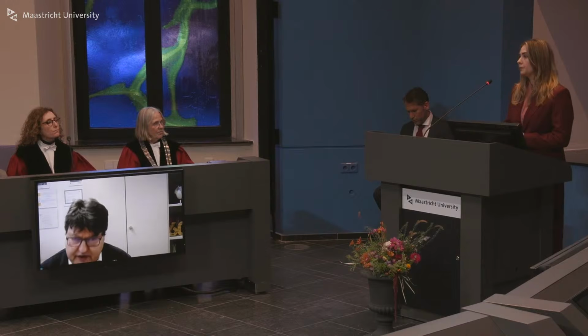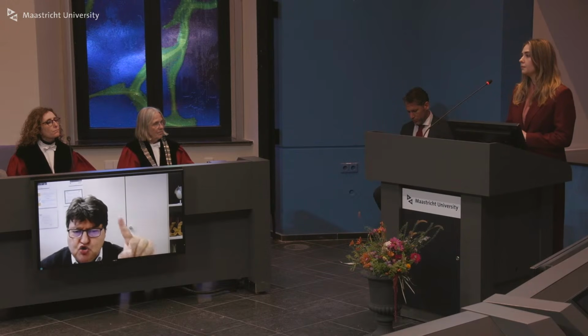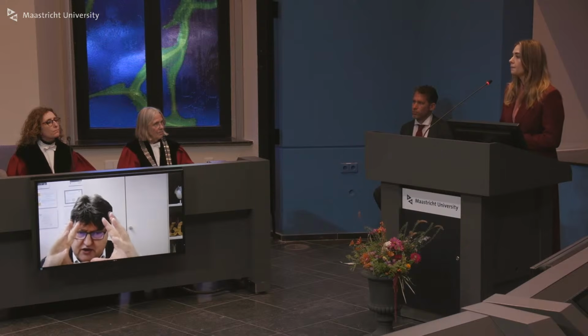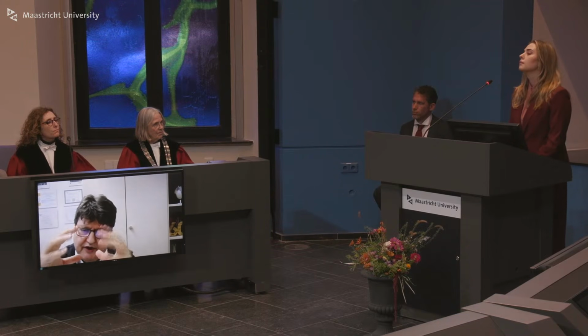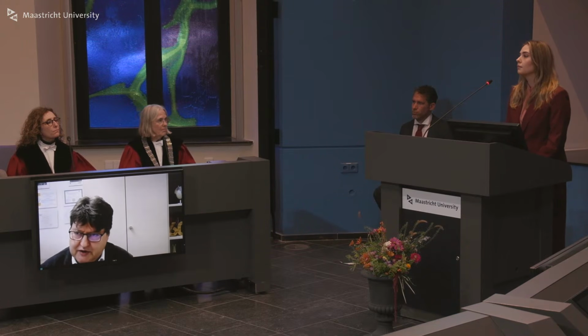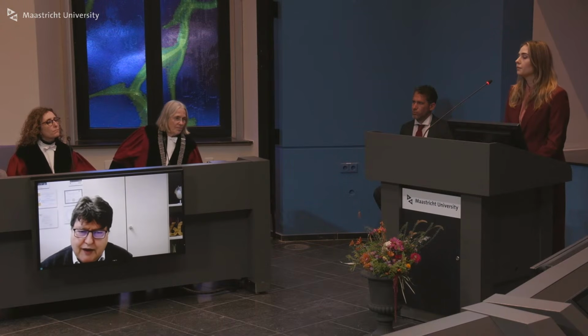Yes, in fact, I forgot to mention, we did EDX analysis to map the elements, to check for their presence, first of all, and also where they were, more or less. And we detected the presence of all added inorganics. If in your case, you have a dual addition in some cases, you have the zinc, and then on top you put either the cobalt or the copper. Indeed.